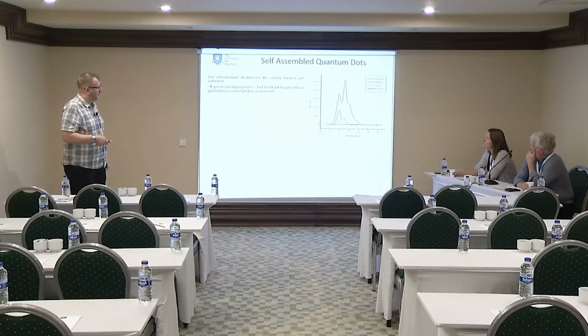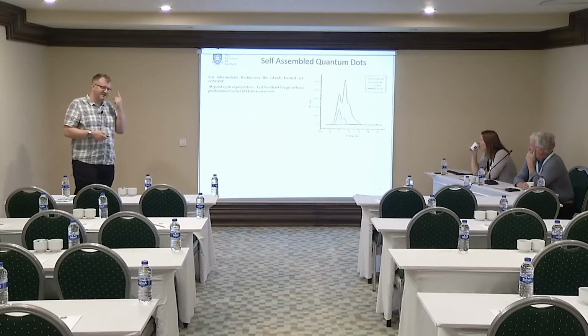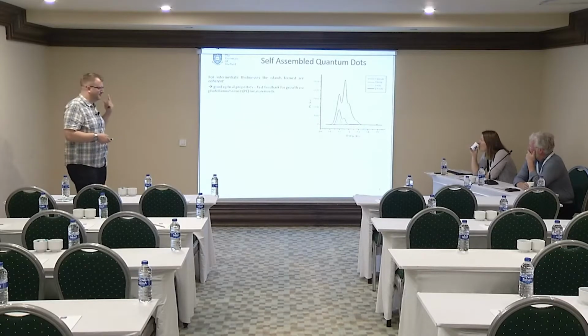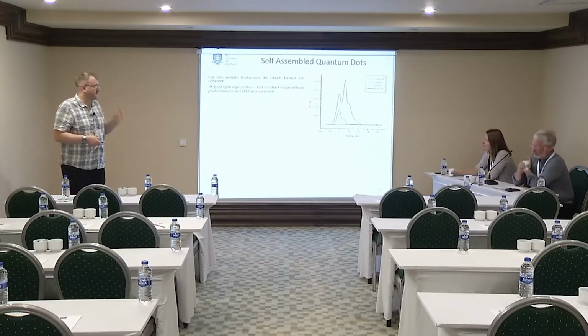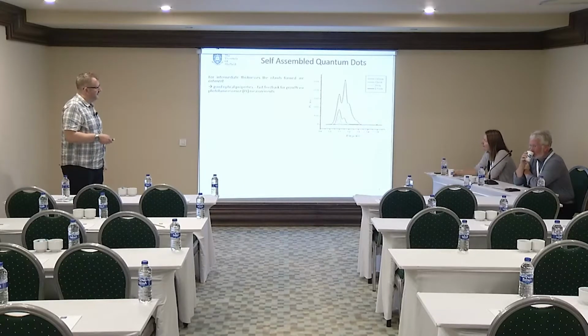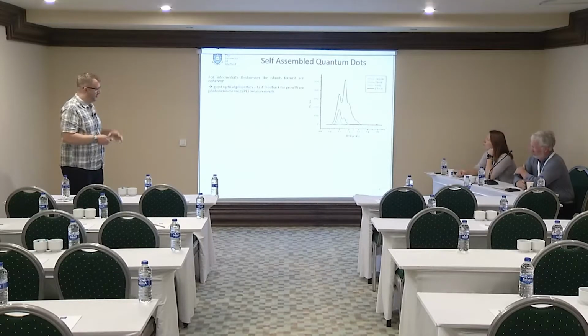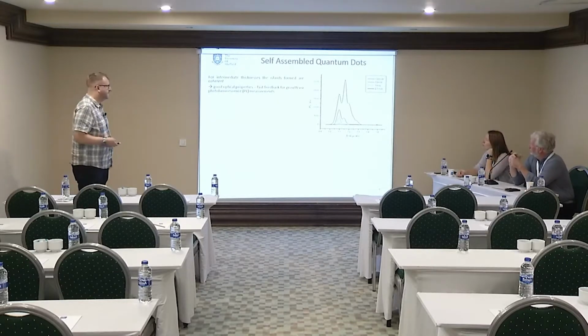If we have a large number of quantum dots, then what we see is an ensemble distribution. Remember, quantum dots, as we're told in semiconductors, have a delta function like density of states. This doesn't look like a delta function. That's because they're all slightly different sizes. But what we also have is effectively standard state filling, s, p shells, and so on. So we have this kind of structure where we're adding more and more electrons and holes to the dots.